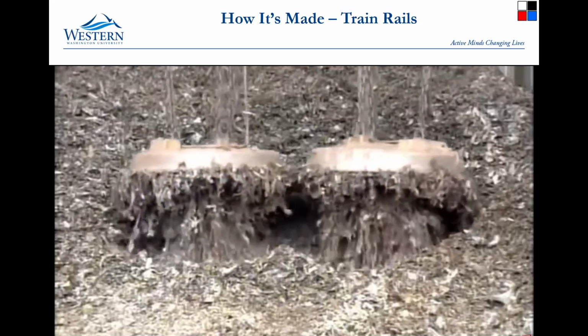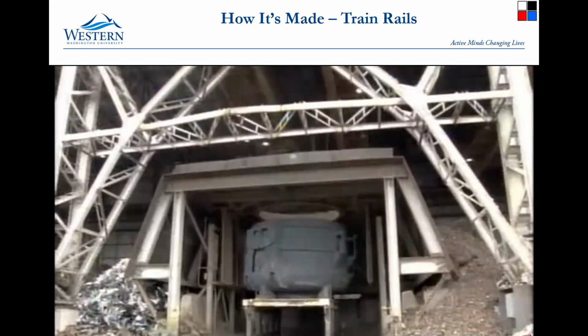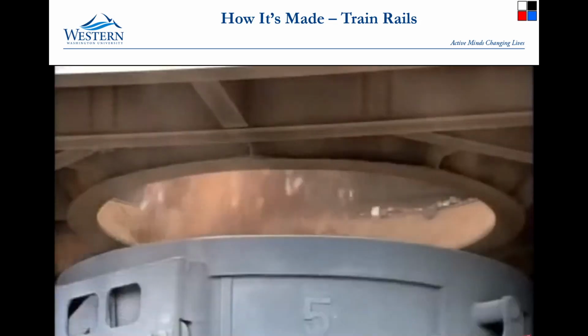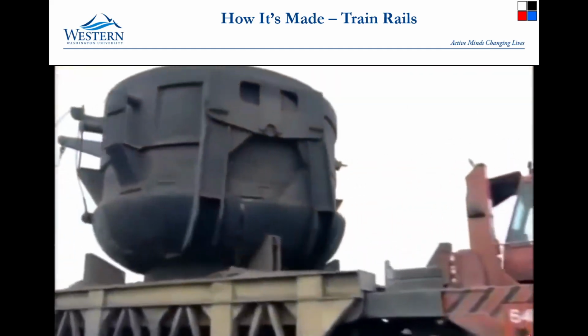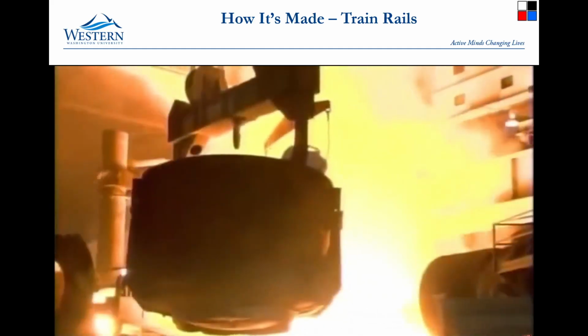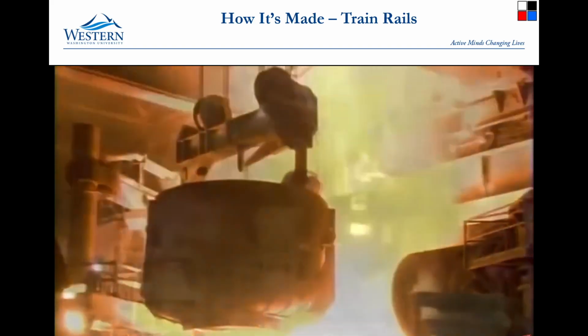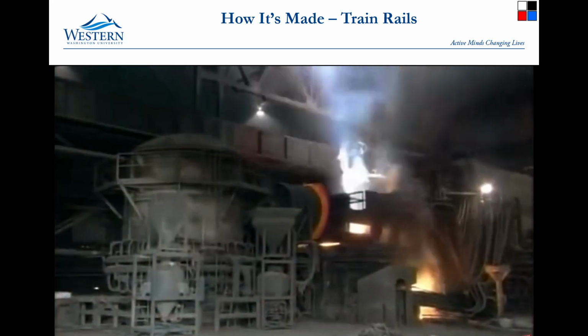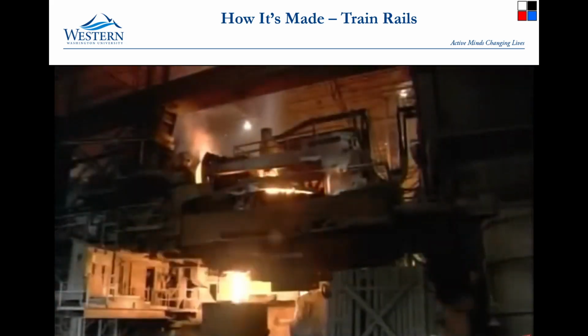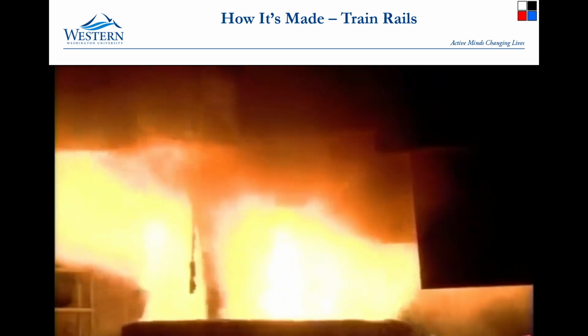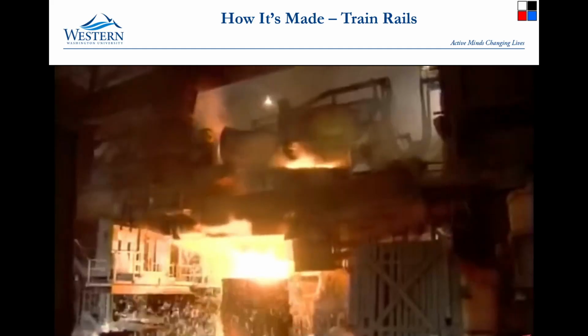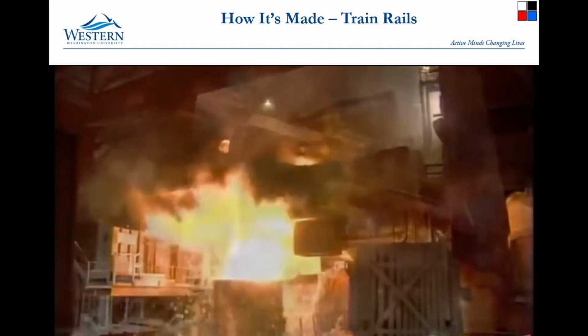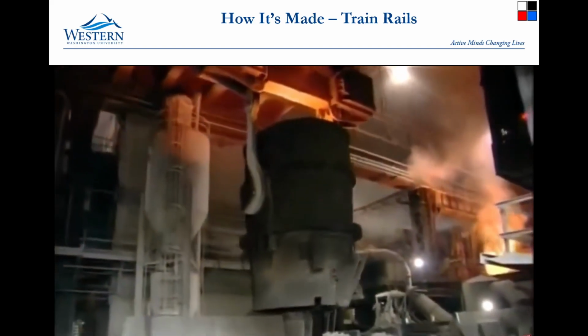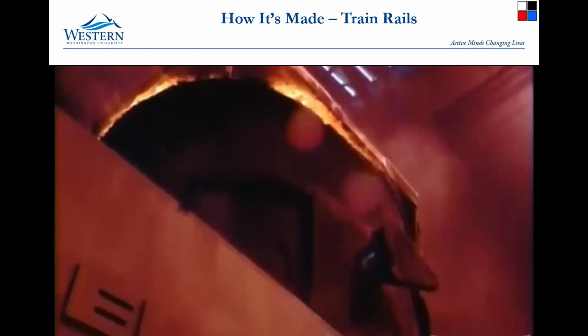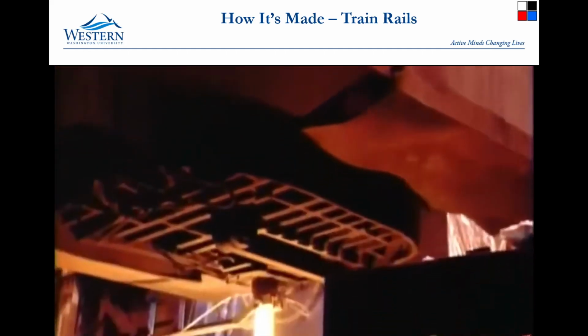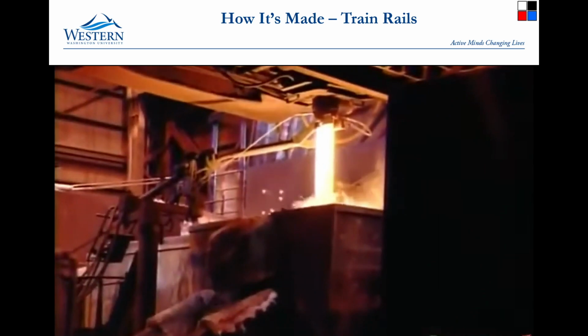Electromagnets pick up the scrap and dump it in a charging bucket. A truck hauls the bucket inside, where a crane drops the contents into a furnace. An intense electric current melts the scrap steel at 1650 degrees Celsius. It then flows into a large brick-lined ladle, where they add carbon, manganese, and other elements to make the steel more durable.